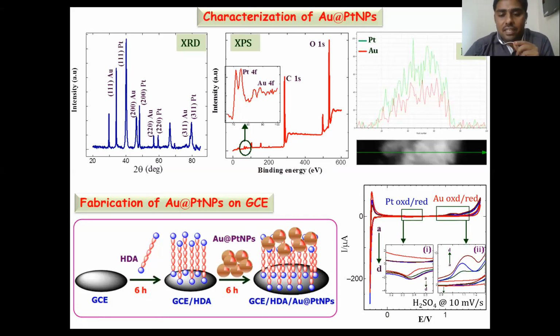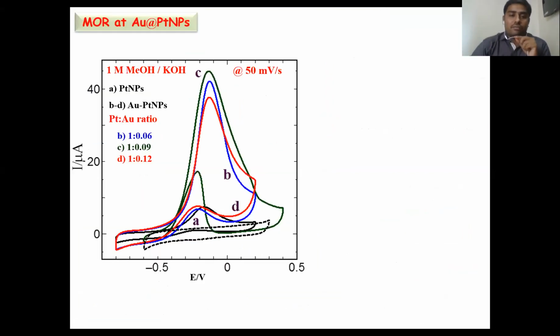The hydrogen adsorption and desorption peaks are very particular for the platinum catalyst, and gold oxide formation and reduction is very particular for the gold nanoparticles. So by seeing these two responses simultaneously in the graph, we can confirm that the gold platinum bimetallic nanoparticles are successfully fabricated on the electrode surface.